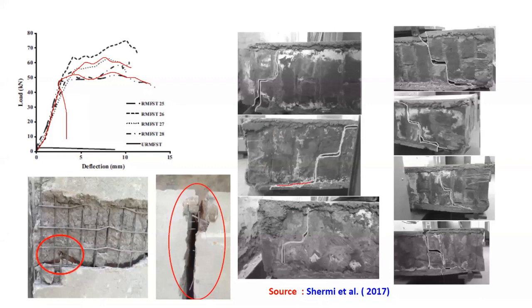The cracks generally happen in the mortar gaps. You can see here that no bricks are getting damaged easily. Only through the mortar gaps were the cracks observed in the study, which proves that mortar is the weakest region in the masonry wall. When we provide this kind of reinforcement, the cracks should happen; otherwise, you can't expect a wonderful bending. The welded wire mesh is yielding, and we can get a perfect ductile behavior.